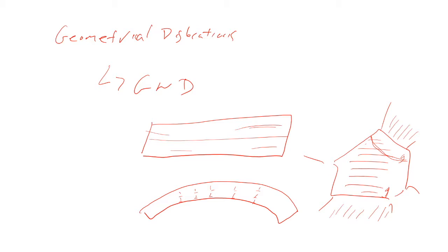That means that there's a size dependence, right? Obviously, this is an edge dislocation. If I make my box and do a very small Burgers circuit, of course I have a closure failure. If I make it large enough, no matter what my dislocation population is there, I'm not going to have a closure failure. So this notion of GND has an intrinsic size dependence.